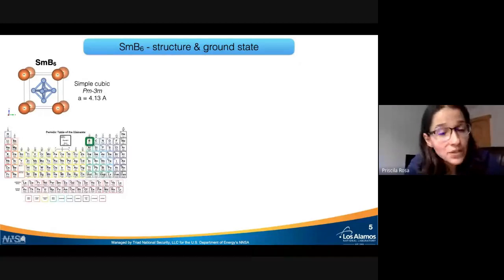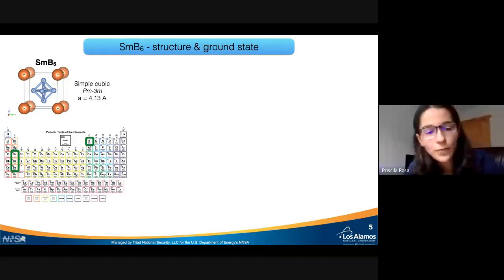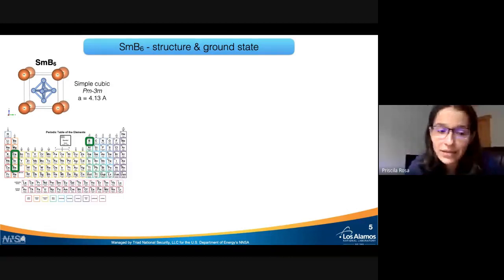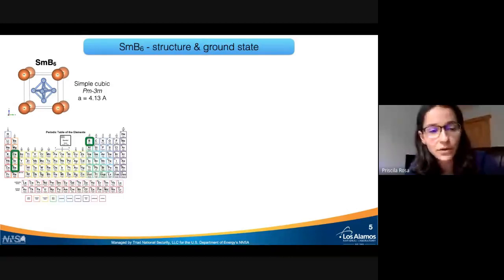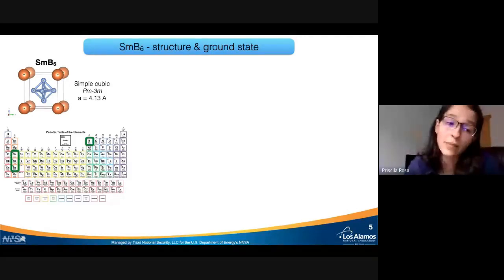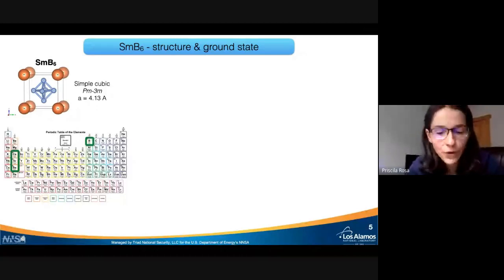And from band structure calculations, we know that boron really needs 2 electrons to be happy and complete its shell. And we know that, for example, calcium, strontium, or barium are divalent, so they give away 2 electrons. So if we have, for example, calcium B6, we have an insulator, an insulating ground state. And that's exactly what happens in the actual material.